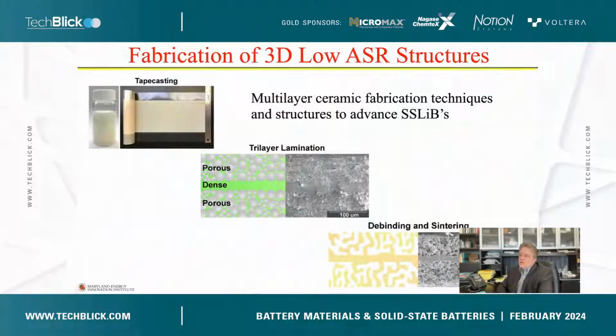To make the structures, it's very scalable ceramic processing. We just do tape casting. We make multiple layers. One layer is dense, just the ceramic electrolyte itself, and in the other layers, we add a pore former. It's polymer spheres, which burn out during a single firing step. You can see that in the lower right here with an example of what we call a tri-layer.